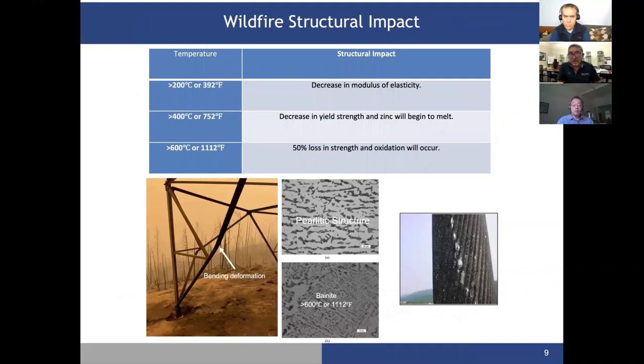What I have for you here is the effect of wildfire on a structural impact. I have defined three ranges of temperatures that I thought are very important to consider about the structures after the exposure to wildfire. Greater than 200 degrees C results in a decrease in modulus of elasticity. Between 200 and 400, changes are taking place, but if the temperature exceeds 400 degrees C, you will see a decrease in yield strength. And also, zinc will begin to melt.